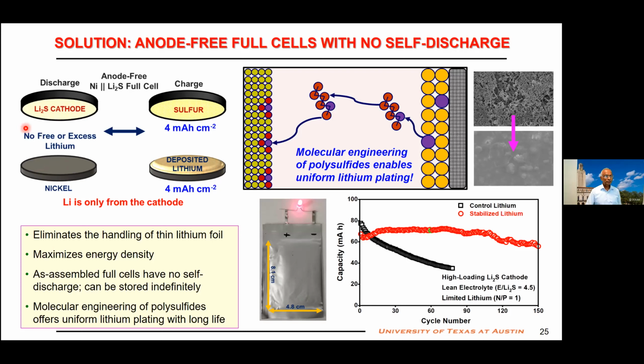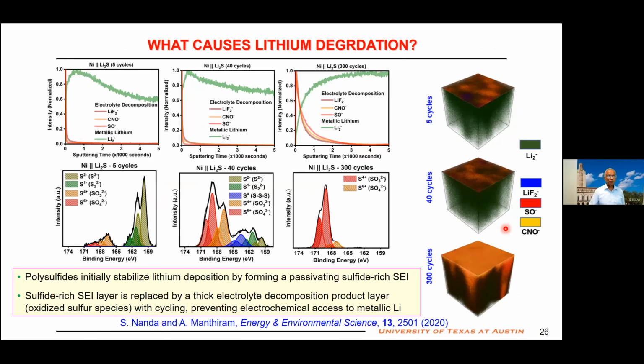So with this, we have gained a lot of understanding and we are trying to use that to make lithium sulfur work better. As you can see here, without controlling the stabilization of lithium metal, you have faster decay, but if you stabilize the lithium metal anode, you can get better cyclability. So let me have a couple of more slides to do this. So what really causes the lithium metal to degrade in lithium sulfur batteries?